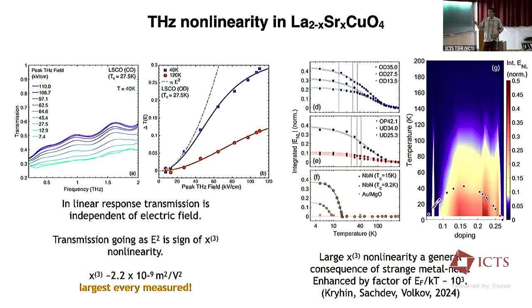I've been telling you a lot about these sophisticated terahertz, this two-dimensional coherent spectroscopy, but we can do lots of different experiments with these intense terahertz pulses. And this is kind of the simplest one you can imagine, where we measure the transmission through the system as a function of the applied electric field. And so if I was purely in a linear response regime, it wouldn't matter how hard I drive it. And so this provides a way of getting a reasonably accurate but kind of frequency-averaged version of the nonlinear coefficient.